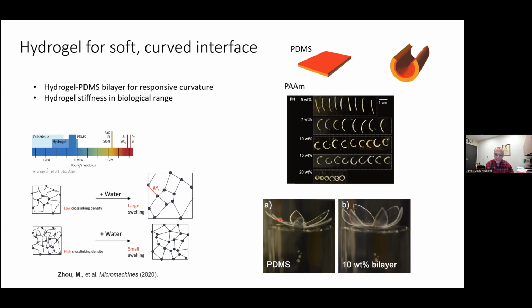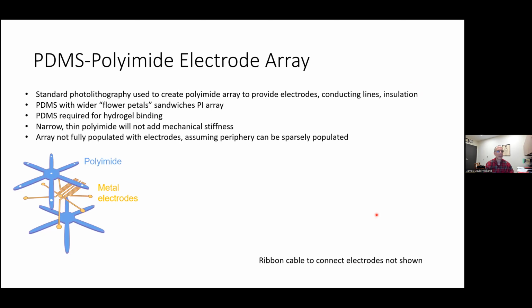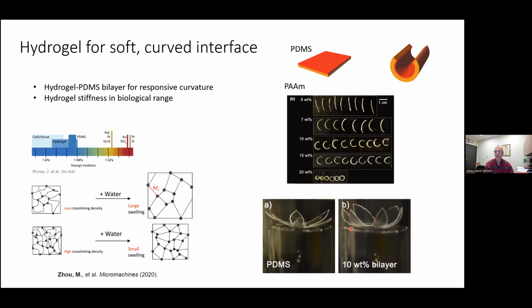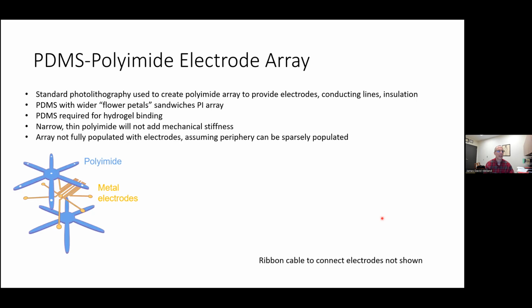And when we do that in two dimensions, this is the PDMS array, but when we add a hydrogel, we're able to add curvature to that. So now we've got something that's spherical and wide and can fit into the eye and take the shape of the retina. So this is just a polymer substrate. We need to add electrodes to this in order to be functional. So here's how we did that.